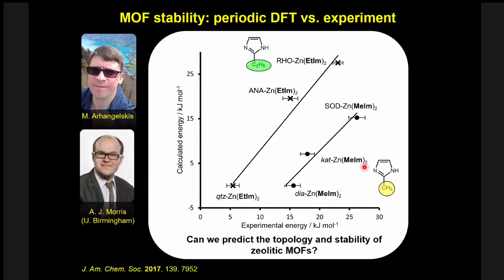Now, measuring these stabilities also got us in touch with a postdoc then, and now running his own research group in Poland, Mihails Arhangelskis, and Andrew Morris in Birmingham, who actually introduced our group to periodic density functional theory calculations. And the nice result was that actually all what these straight lines are showing here, to put it in a nutshell, they're showing that we can calculate the stability of MOFs and find out that the calculated numbers are really well correlated.